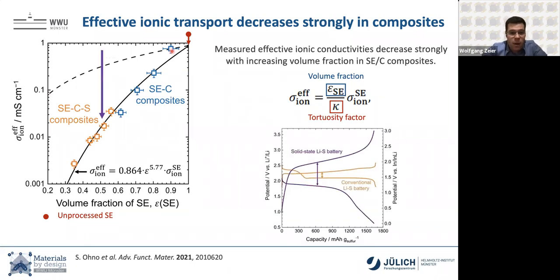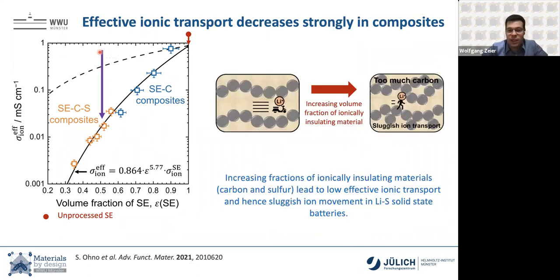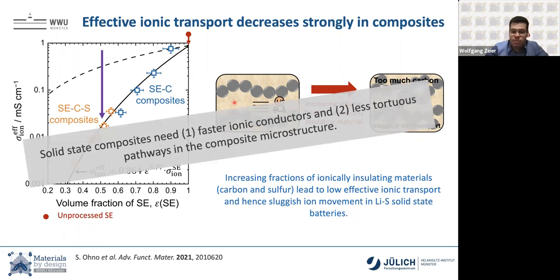What does this mean? Well, by this drop of the conductivity, we build up a much larger resistance in our cell, because ion transport in these composites is no longer fast. So initially it was fast. We put a little bit of carbon in there, and from a race car, it becomes a Vespa. And the more carbon you put in there, the slower your lithium becomes, because you're just increasing your fraction of ionically insulating material, the carbon and the sulfur. We really have sluggish ion movement in these solid-state batteries.